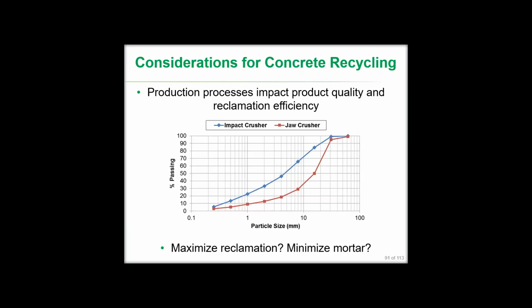So depending upon your goals and depending upon the material that you have there, sometimes minimizing mortar is a good thing. Again, for example, if you have a concern with the quality of the durability of that mortar, eliminating it's a good thing, but you have to recognize that you may only wind up with a 40% volume reclamation for coarse aggregate. You may have 60% fine aggregate to deal with, whereas if you are trying to maximize the reclamation and you have no concerns about the quality of the aggregate, the jaw crushers and things of that nature that don't produce quite as many fines may be the better option.